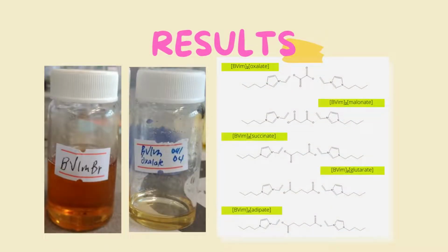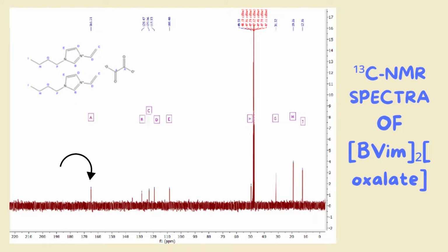The dicarboxylate ionic liquids were synthesized from the precursor halide ionic liquid, and the products were noticeably lighter in color. They were slightly less viscous than the precursor IL, and it was observed that increasing the alkyl chain length of the dicarboxylate increases the viscosity of the ionic liquids. The appearance of a chemical shift at around 165 parts per million in the carbon NMR spectra of the dicarboxylate IL signifies the presence of a carboxylate group from the dicarboxylates, indicating that the dicarboxylate IL was successfully synthesized.